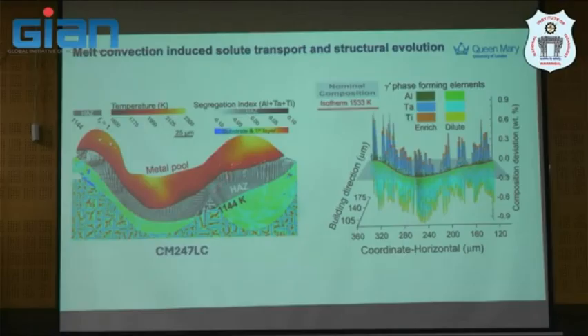And then the metal here is actually, this is a melt pool, heat affected zone, solidification progress here, and this is still in liquid here. So you can identify based on the gamma prime forming element. Again, this is not gamma prime yet. It's just a forming element.